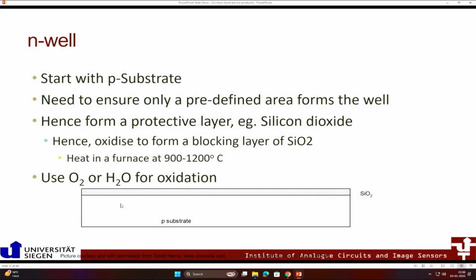इसका advantage है silicon का top surface तो oxidize हो जाएगा. तो oxidize करने के लिए पहला काम करते हैं कि हम एक furnace में 900 to 1200 degree Celsius पे heat करते हैं, wafer को गर्म किया हमने. Okay, और उसके बाद either using oxygen or water, wafer top layer को oxidize करते हैं. Temperature बढ़ा हो, one of the oxide form हो जाएगा. H2O के साथ oxidation जल्दी होती है, but then आपको hydrogen बचा हुआ उसको निकालने का एक problem होता है.